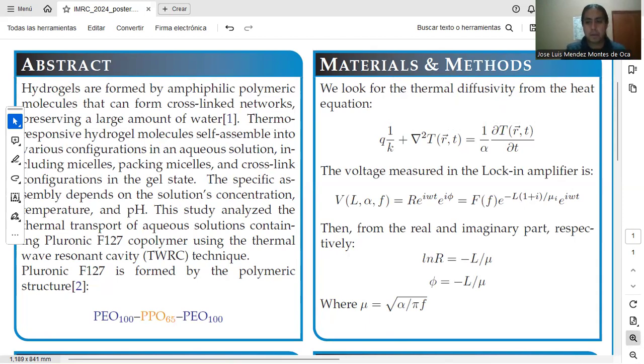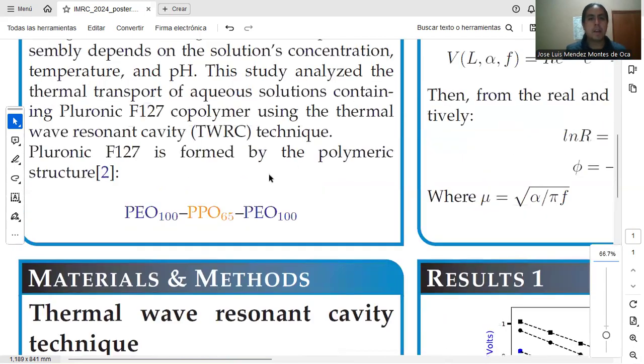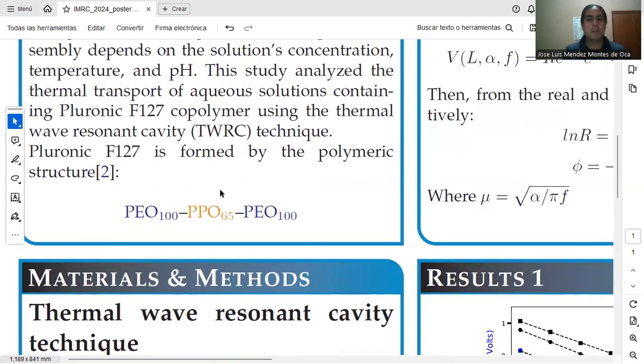Well, pluronics are copolymer materials that have a polypropylene oxide block in between two polyethylene oxide blocks. And the polypropylene oxide block is hydrophobic, and the polyethylene oxide blocks are hydrophilic. Well, in general, these molecules are hydrophilic, and can be in solution in water if the concentration is low and if the temperature is low.